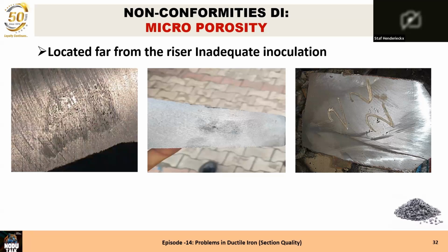You can see here some of them that I had from real pictures, and you can see a number of them, all very small porosity, very close to each other. It's mostly far from the riser due to inadequate inoculation. Why?